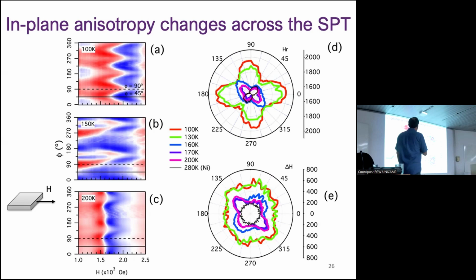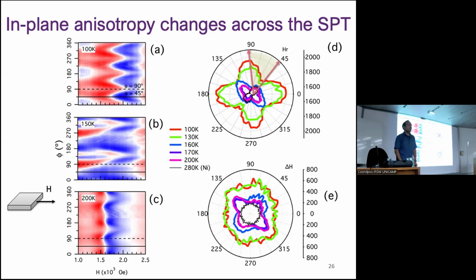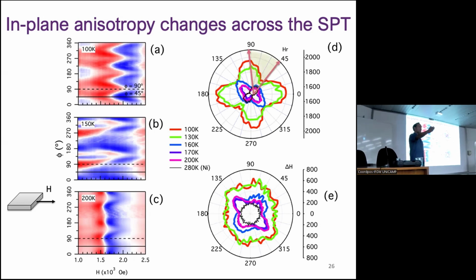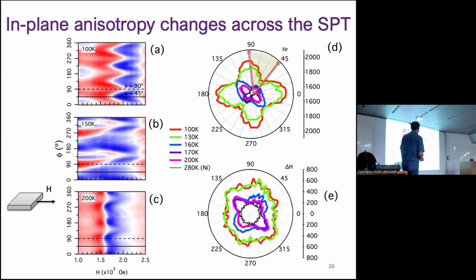So the first one here, those maps are the resonance, and you see that there is matching. So you have this 4-fold, and at low temperature you have this kind of 1-fold, 2-fold actually, 2 axes here. But then there is a rotation of 45 degrees of the easy axis of the nickel sample. So I have an easy axis where the magnetization wants to align at high temperature, and then at low temperature it rotates 45 degrees, naturally. Okay, and that's very interesting.